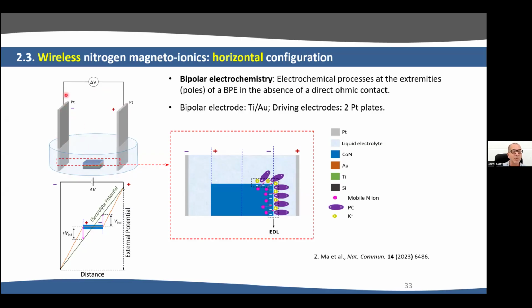When we apply voltage to these two platinum electrodes, there is a phenomenon in the material, which is actually titanium gold cobalt nitride, called bipolar electrochemistry. So what happens? Here is the positive platinum, and the part of the film that is facing the positive platinum gets negatively polarized. And on the other side, we have a positive induced charge. So this is a bipole, okay? Now, if this negative charge induced through bipolar electrochemistry is sufficient to release the nitrogen away from cobalt nitride, we may be able to generate magnetism here. And actually, we did the experiment.